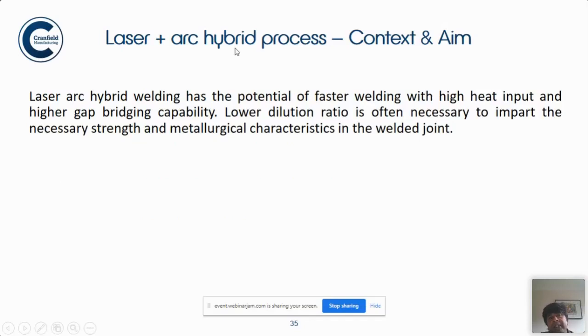As I said in the beginning, I will talk a little bit about the laser plus arc hybrid process. So why do you use laser? A, for productivity, and B, for very accurate welding, like in e-mobility, where we are joining copper which is say 0.5 millimeter or 1 millimeter thick, and therefore you need a very accurate heat source. The other important thing is that for thicker structures, laser plus arc processes are used. Laser plus arc hybrid welding has the potential of faster welding with a high heat input and higher gap bridging capability. Lower dilution ratio is often necessary to impart the necessary strength and metallurgical characteristics in a joint.